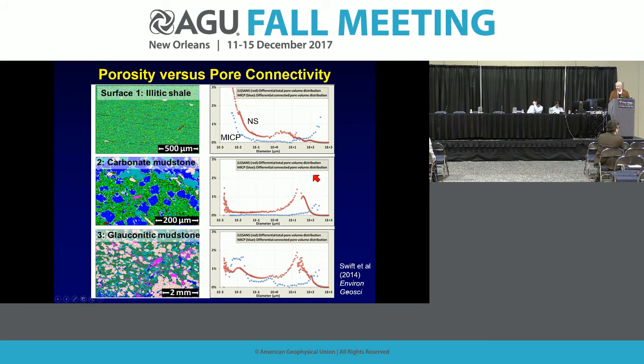This is not true when you look at these other rocks that have a bit more coarser texture, such as a carbonate mud, or even a glauconite mud. You get very different patterns depending on whether we're talking about pore throat connectivity or the pores themselves. But the point here is we can actually start quantifying these distributions, their size distribution and their contribution to porosity. That's the good news in terms of how to deal with a complicated earth material.